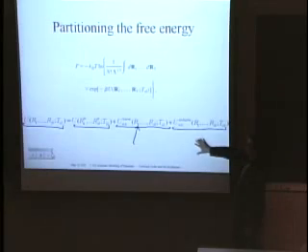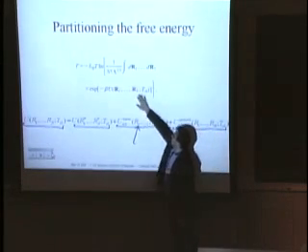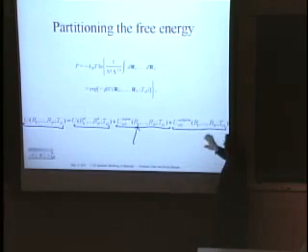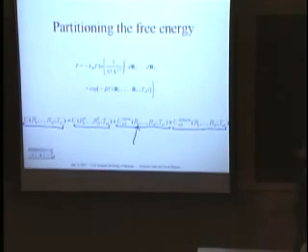In the case of a solid, this makes a lot of sense because it's fairly easy to calculate explicitly the integral of the partition function for the harmonic term, and the anharmonic part is reserved for an explicit integration done using molecular dynamics.